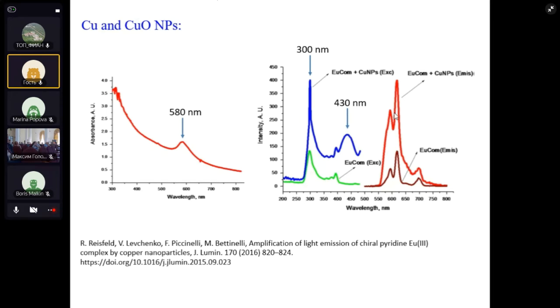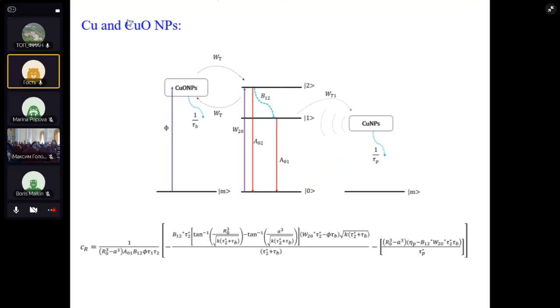It's a polymeric system. And then we were able to explain their results by taking into account, and this is the important point in this work, that copper is very, very easily oxidized. And so copper oxide nanoparticles are also in the medium. And we have shown theoretically that it plays a very crucial role in the whole process of enhancement in these composite systems. Okay, the situation is quite different from the case of silver nanoparticles. And this is an energy level diagram to illustrate the model we have used.